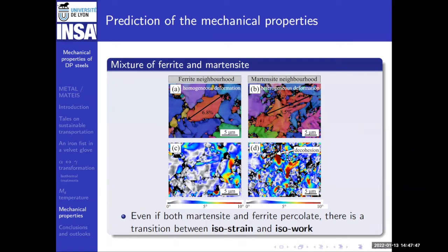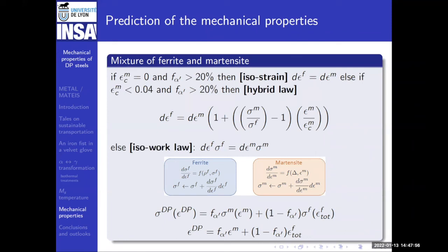This transition between isostrain and isowork, from the investigation of the microstructure, led to a law of mixture, which is organized this way. So we say that if epsilon is 0, then it's isostrain. If epsilon is smaller than 0.04, it's a hybrid law going from isostrain to isowork depending on epsilon of martensite, the deformation of martensite. So we start from isostrain, we end up with an isowork law, and in this domain, it's this law that goes from this to this expression. And once we have the coupling between the deformation of ferrite and martensite, by looping on the equations that I previously presented, we can predict the stress and strain of the dual phase steel.